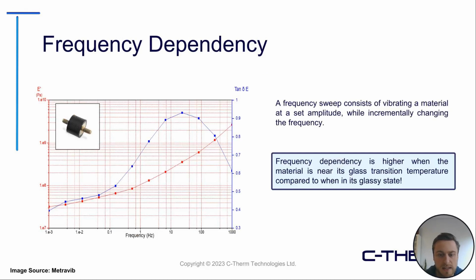And then just to look at some frequency dependency behavior without temperature, we can also do frequency sweeps. A frequency sweep consists of vibrating material at a set amplitude while incrementally changing the frequency. As we can see here on the left, this rubber damper was highly dependent on frequency, peaking at about 20 hertz.